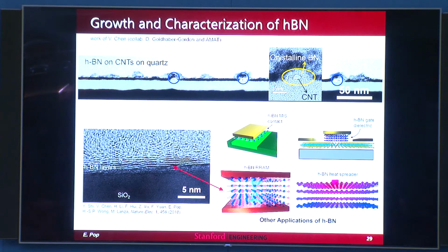Maybe one word about hBN, and this is also inspired by some of Jing Kong's work. In fact, I hired her former student as a postdoc when we started working on this. Most recently, we've been able to grow hBN directly onto carbon nanotubes, so that's kind of cute. This is actually work done with Applied Materials. We're growing directly onto carbon nanotubes. Carbon nanotubes can withstand the growth temperatures.